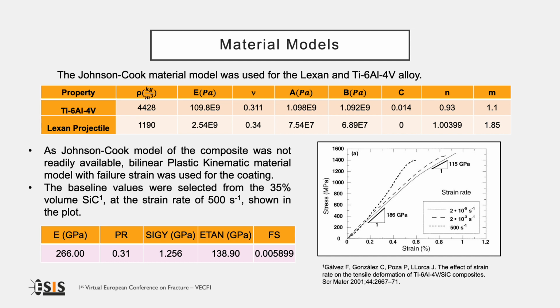The baseline values for this material model were selected from the 35% volume silicon carbide, and the material parameters are reported in the table: the elastic modulus, the Poisson ratio, the yield strength, the tangent modulus, and finally the failure strain. In particular, this material model is based on an element erosion criterion which deletes the element once the strain is higher than the maximum equivalent plastic strain, which is defined by the user.